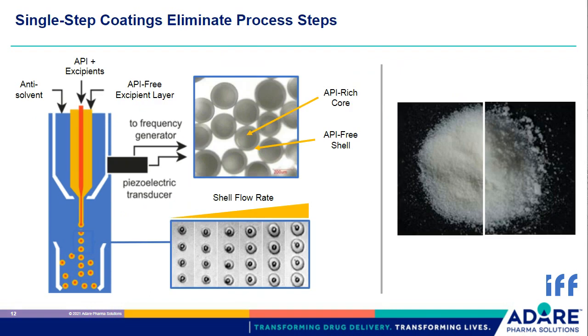Same nozzle configuration can be used for generating core shell particles. The only difference is the presence of a concentric nozzle, basically adding another fluid layer to enable the generation of a core shell structure. This allows for a single-step coating mechanism while maintaining a small size. By tuning processing variables, we can precisely control particle size, but also the core shell ratio, as you can see in the slide.